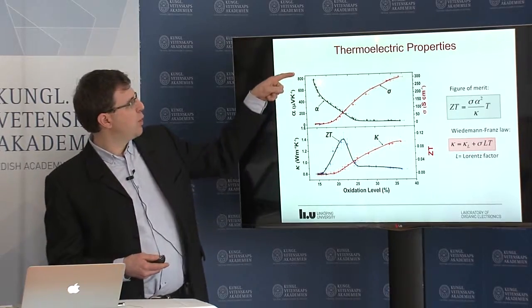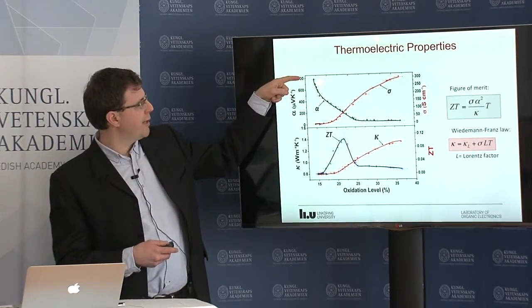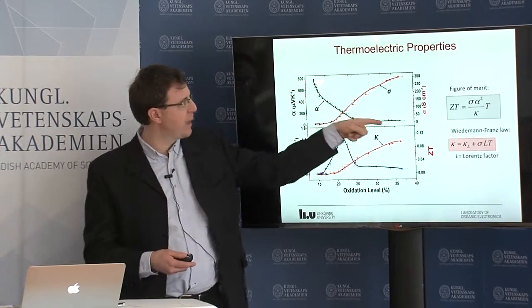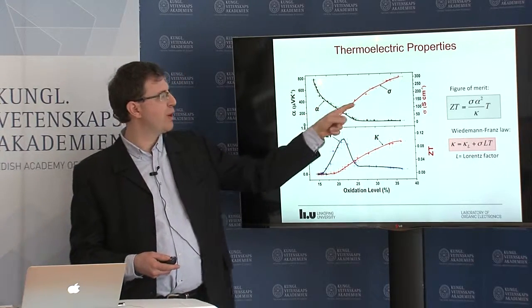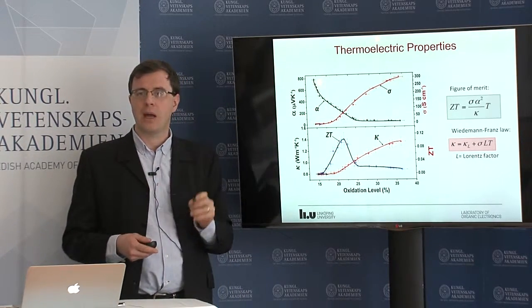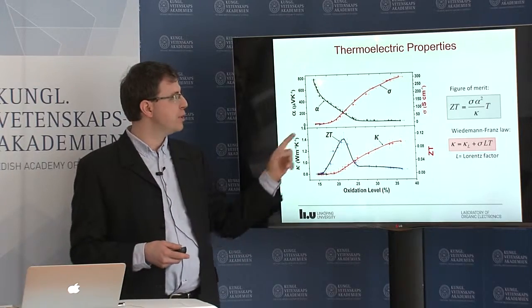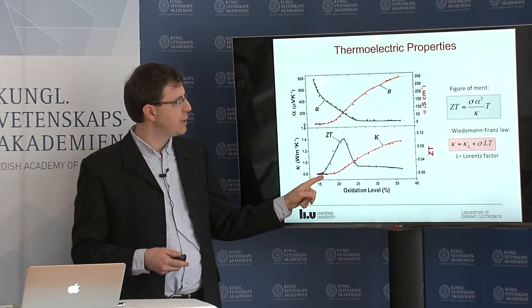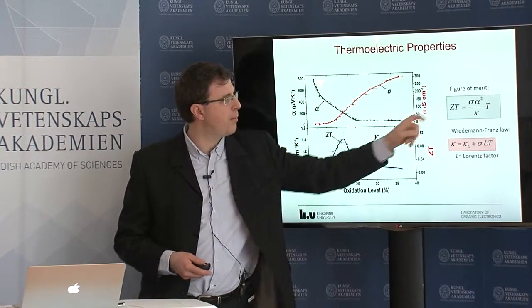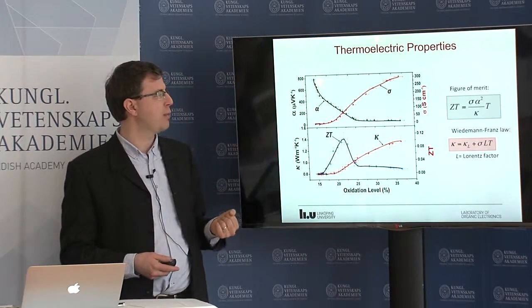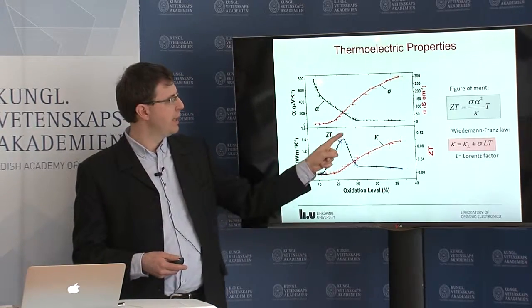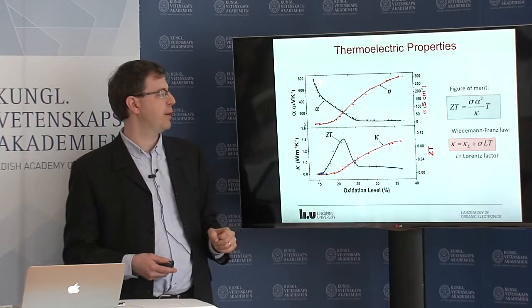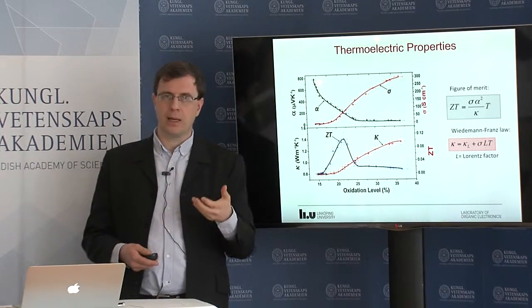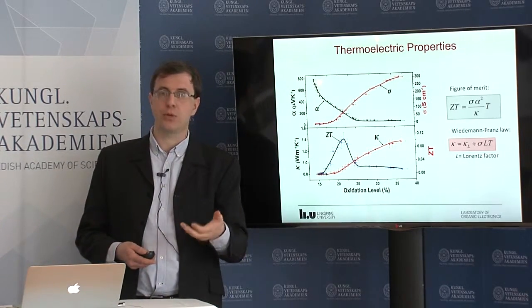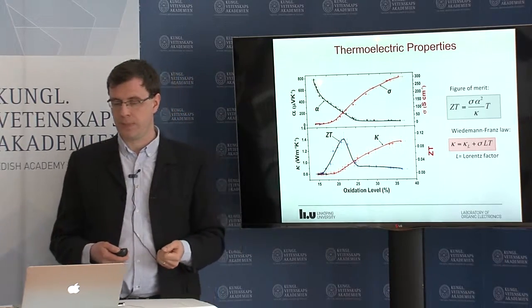But we also have, when we increase the oxidation level, the decrease of the Seebeck coefficient. So those cancel each other. And somewhere in the middle, there is an optimum. And this is what we found here. The optimum for ZT, which describes the conversion efficiency, is about 22% there. And there, the optimized conducting polymer starts to be a thermoelectric material.